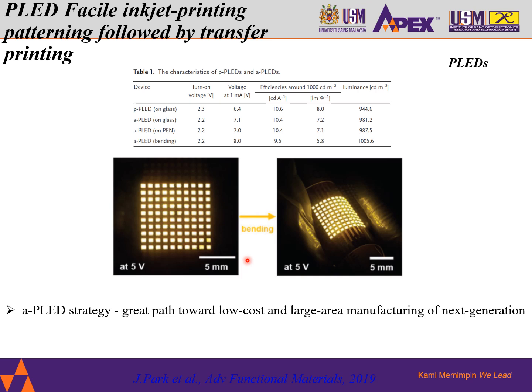Thanks to their method of easy patterning and no solvent damage to organic layers for the transfer printing process, excellent performances of a-PLEDs were successfully demonstrated on both rigid and flexible substrates, and various pixel shapes and features were highly customized. Demonstration of all solution process array showed a promising potential for all solution process commercial displays. The a-PLED strategy is believed to have a great path toward low cost and large area manufacturing.